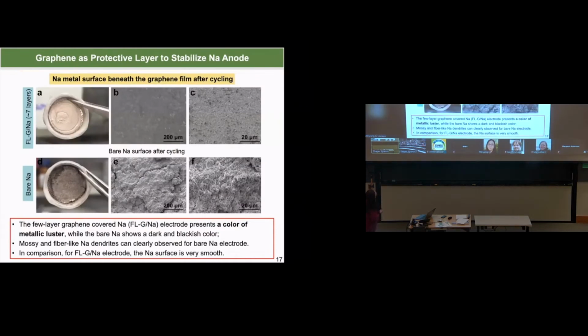Okay. So here I want to show another image for this work. You can see that this is after we disassemble the cell. This is the surface of sodium metal, the one covered by the graphene film. You can see it's very flat. For a bare sodium system, you can see the surface is very rough. This also shows that the sodium metal is well protected by this graphene film design.